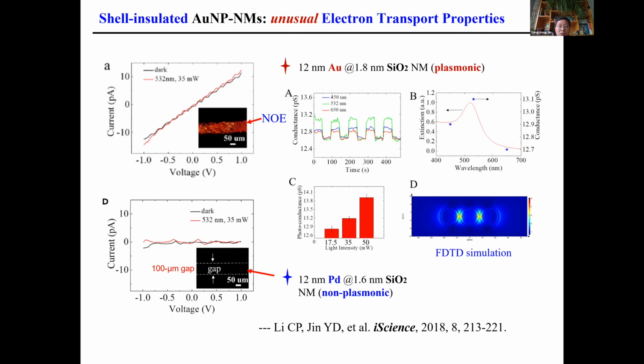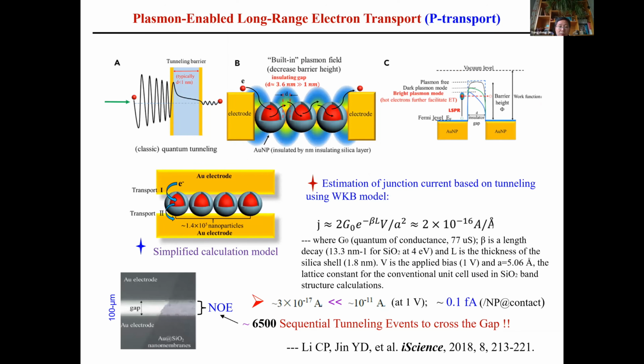The IV response corresponded well with the LSPR profile of the particle. In a control membrane made of 12 nanometer palladium and similar thickness of silica shells, there was no current transfer through the junction. We also did some simulation based on tunneling using the WKB model. Even when we use one row of nanoparticles as a simplified model, we found that the calculated current is still a few orders of magnitude lower than the value we measured. Note that there are almost more than 6,000 sequential tunneling events to cross the gap. So that is amazing. It reveals unusual electron transport in our systems.